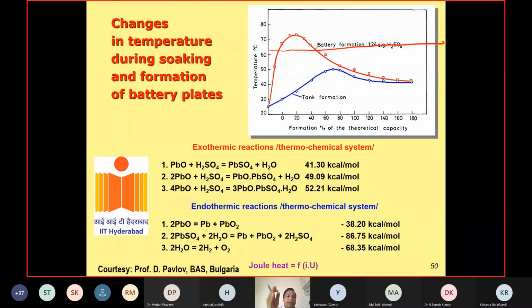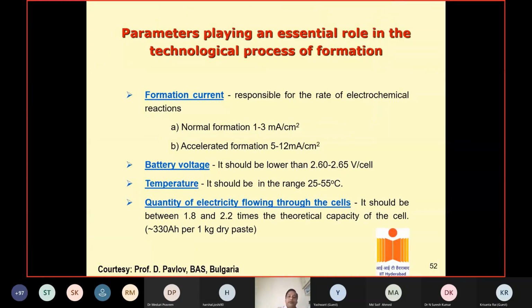During soaking and formation, the battery temperature should be taken into account. So we do the formation. Generally, for those who are interested, 1 to 3 milliamp per centimeter square current is required for the lead acid cell. If it is 35 centimeter square, as you see here, we put around 100 milliamps, minimum around 100 milliamp current. For accelerated formation, you can go even 3 to 4 to 5 times more than this.